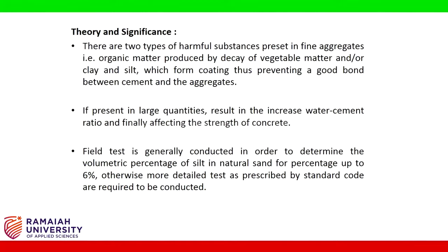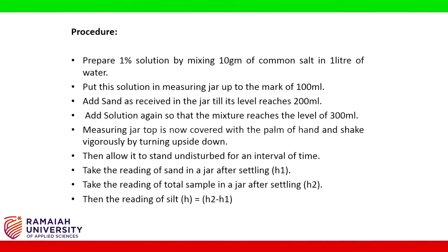This finally affects the strength of concrete. The field test is generally conducted to determine the volumetric percentage of silt in natural sand for percentages up to six percent; otherwise more detailed tests as prescribed by standard code are required. Procedure: prepare a one percent solution by mixing 10 grams of common salt in 1 liter of water.